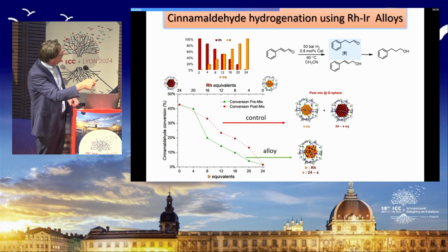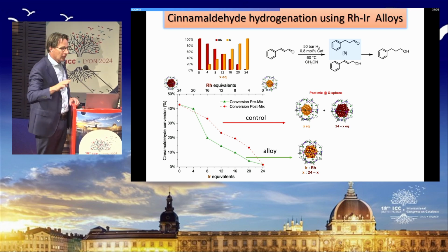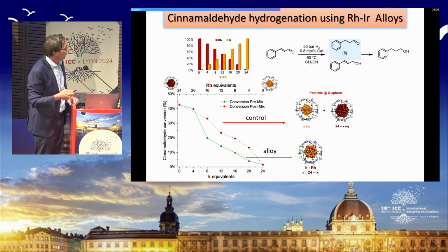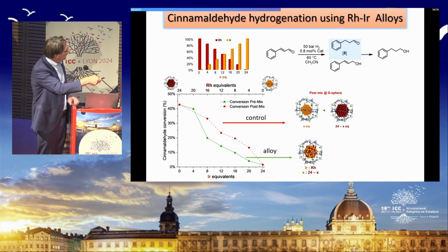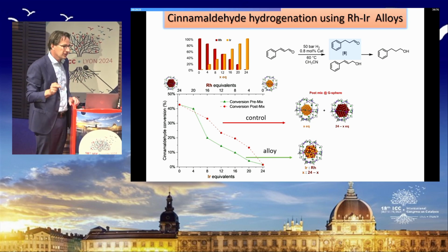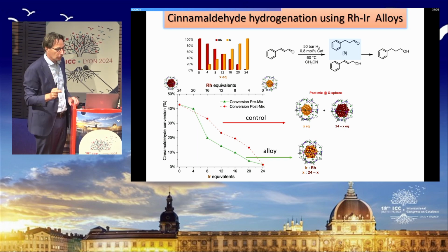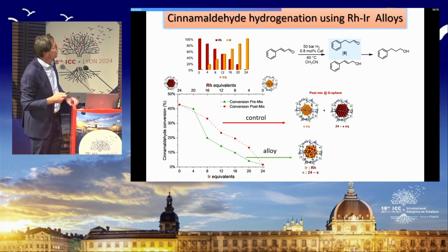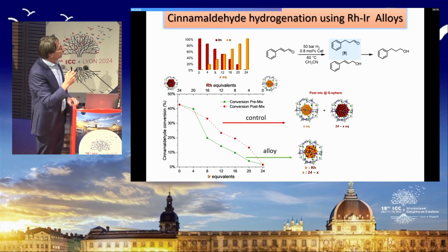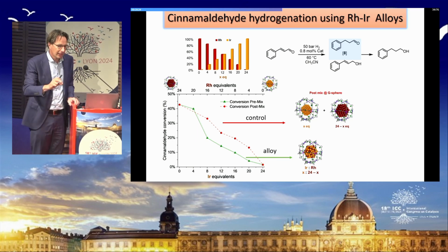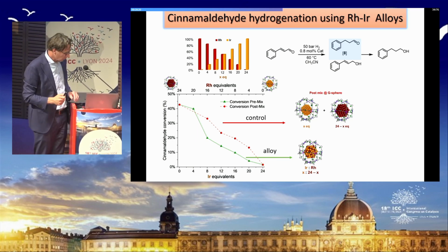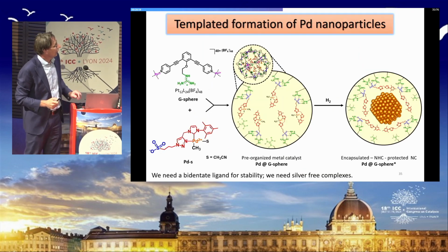So here you see that alloying leads to less reactive rhodium-iridium complexes. And from 16, we no longer see the reactivity of reduction of the solvent, so we no longer see byproduct. I think the most important message from this slide is that we can make alloys also by just making mixtures of different complexes.